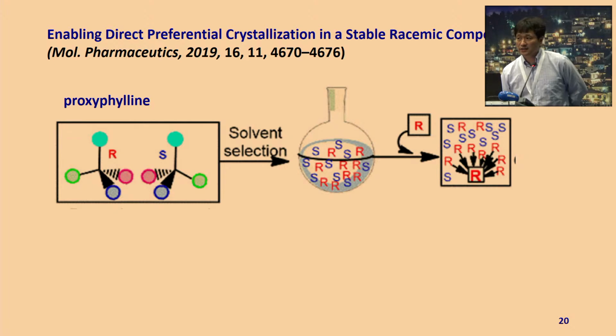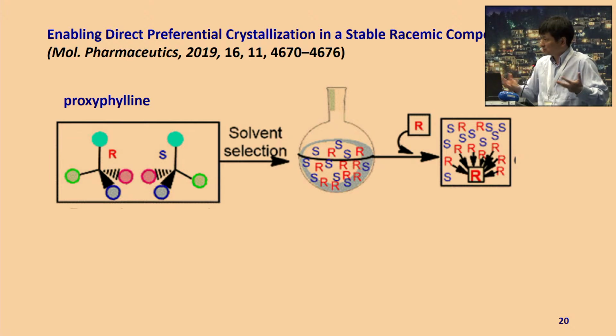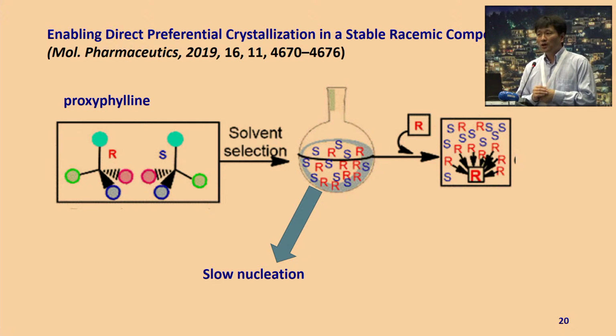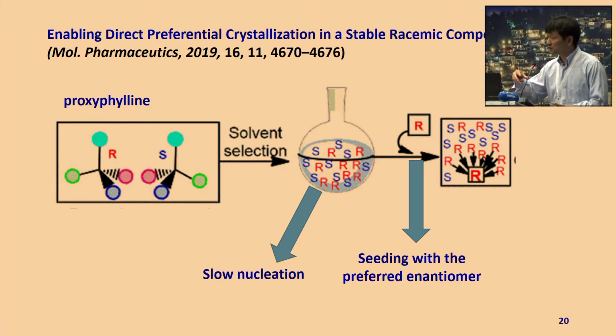In this case, this compound can form a stable racemate, so separating them into pure enantiomers is a challenge. He was able to show, by identifying a suitable solvent where the racemate can only crystallize slowly, that you can slow down the kinetics. Then once you form the solution, you can dissolve the racemate in the solvent and add a seed of the desired enantiomer crystal. Then this seed will induce the crystallization, the growth of this phase, to achieve the separation.